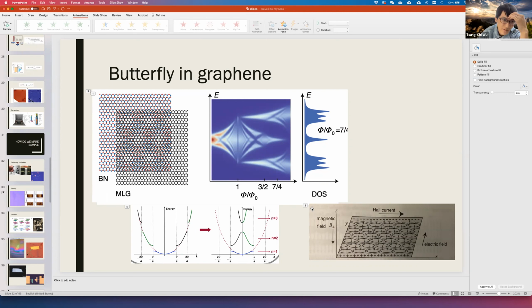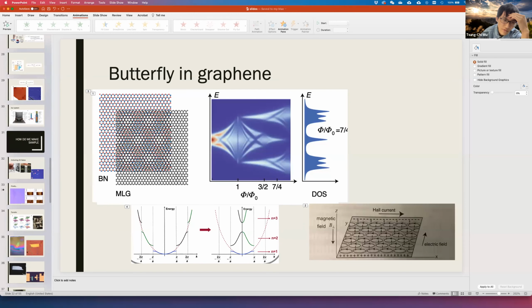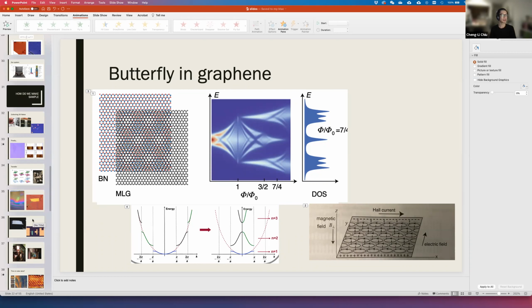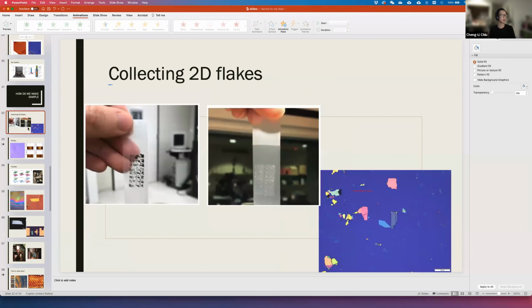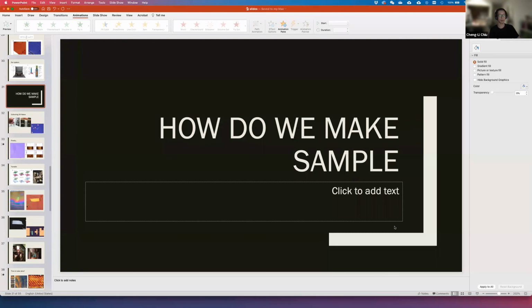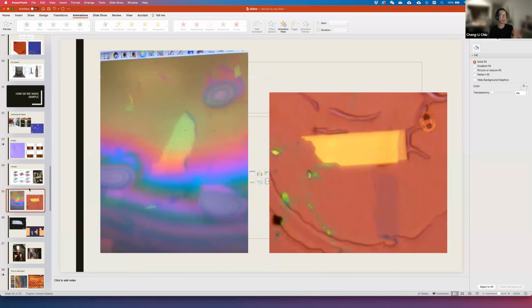Okay, so basically just be careful about the alignment between boron nitride and the graphene. Yeah, but sometimes you want to align them to get more effects. Oh, okay, got you. Okay, thanks. How do you actually align them though? So when you scratch the flake, for example, when you try to cleave a crystal, it tends to cleave along some natural direction. So if you look at the flake, a lot of the time they have straight edges, and those straight edges, if you measure them, have some 120 degree or 60 degree angles.